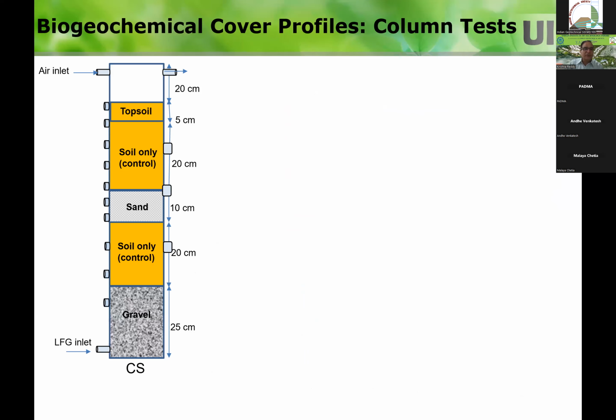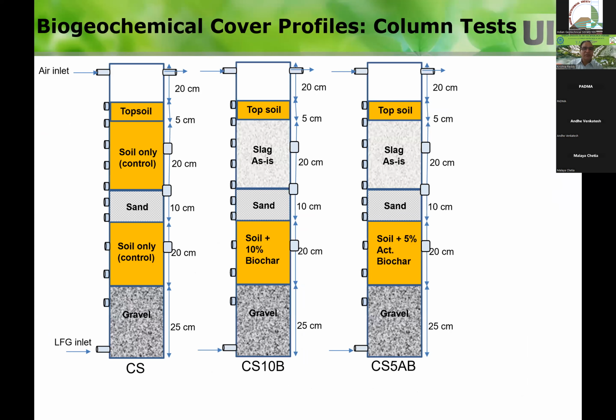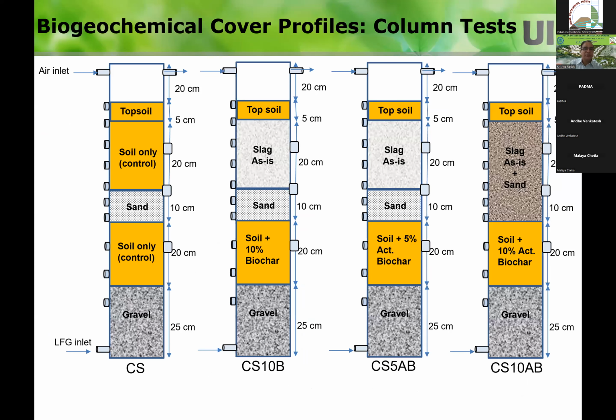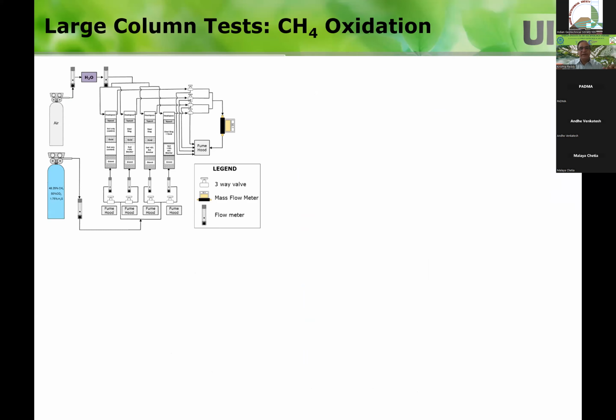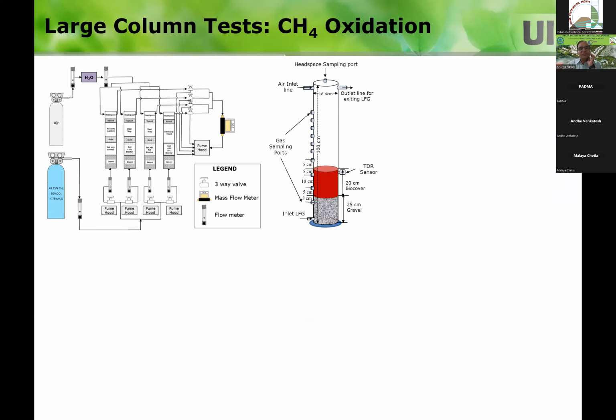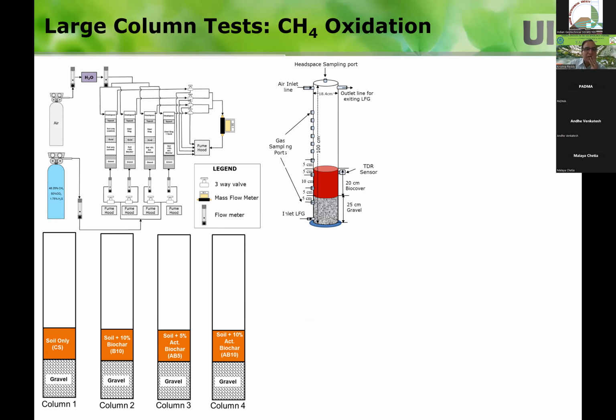Now, we looked at the biochar amended soil, we looked at the slag, right? But we want to use them in combination. So then we tried to do these column experiments in combination with the biochar amended soil and the slag. How we did it is in a sequential order. So let's say we have the column, and we have different columns, the 4 columns. In one, initially we put the gas distribution layer. Basically, we put the gravel at the bottom.